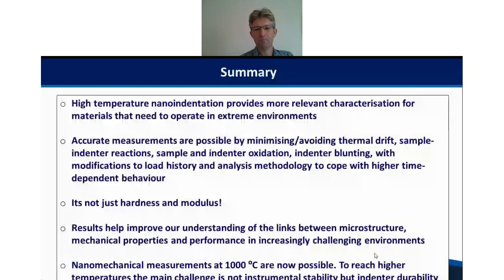You need to take into account minimizing or avoiding thermal drift by accurate temperature matching, and active control of the tip and sample heating to get a constant temperature in that contact zone, so-called isothermal contact. We need to avoid indenter-sample reactions and indenter oxidation by accurate environmental control. We need to consider indenter blunting, and we also need to account for any time-dependent deformation in terms of how we set up the test and how we do the analysis to mitigate this.